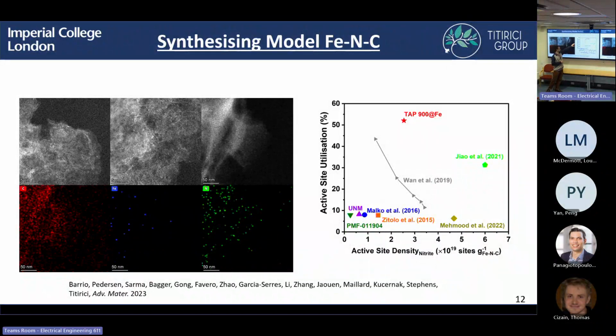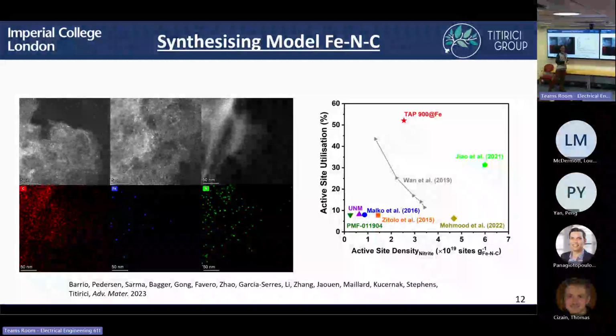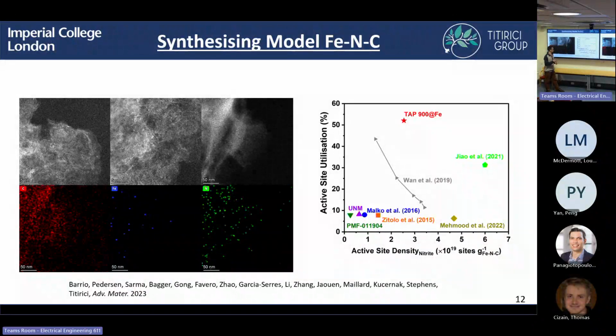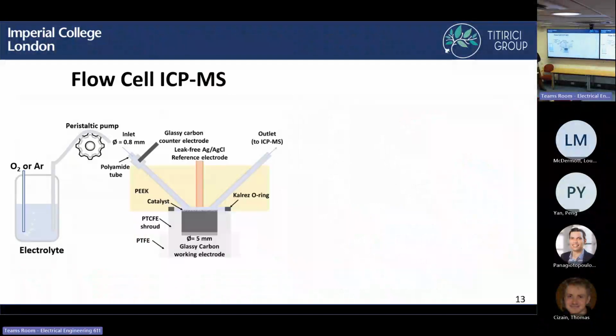And we can also obtain this while having a relatively high active site density. So we could have a high utilization of active sites and a high number of active sites. Whereas you can see in the literature, most materials have around 10% utilization. So now we've confirmed from our previous work that we could have this really porous material where most of the active sites, if we probe them, will actually be used in a reaction. And so we've made our model iron nitrogen carbon material. So now we can actually go on to the title of the talk, looking at the iron dissolution.